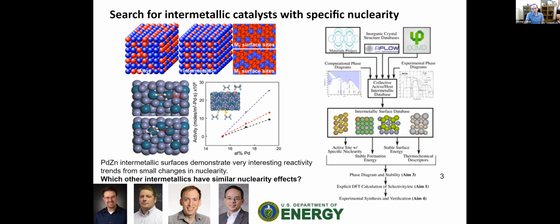But if I form it out of a very, very strongly ordered intermetallic, I can find composition regions where we go from maybe isolated active atoms, let's see if these are isolated palladium atoms. And if I change the composition just a little bit from about 15% palladium in a zinc lattice to about 19%, the atom that gets substituted forms a trimer on the surface.